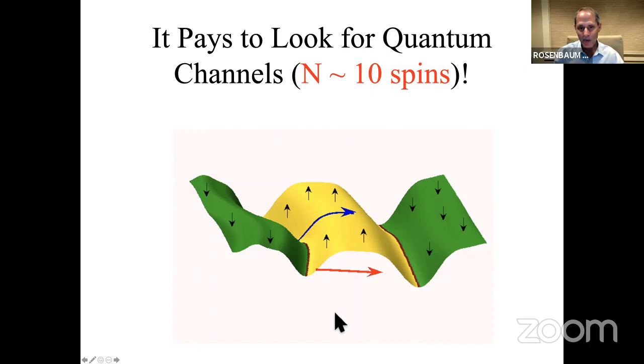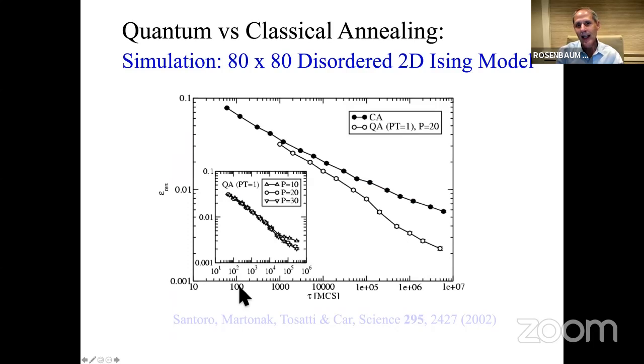So the quantum speed up comes from the fact that if I have two domains here, the green one's down, separated by an up domain, if I want to now get closer to the ordered ferromagnet, I classically flip each of these spins one at a time. But quantum mechanically, I can get a response on the nanometer scale with roughly 10 spins flipping at once from our fit. So that's the origin then of the quantum speed up here. Now this led to a number, and this is old work. I know, and I've learned in this conference already, a lot of more modern work.